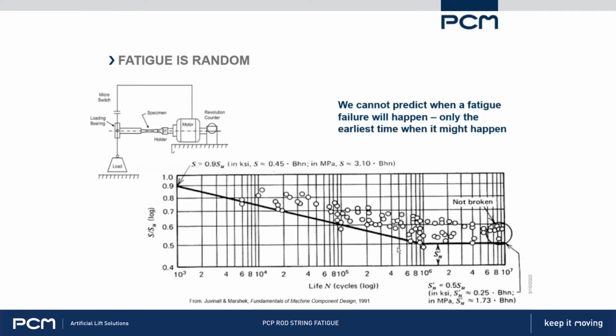And you can see there's a large amount of randomness here. So for example, at 0.6 or 60% of ultimate, the first failures are happening around 100,000 cycles, and we go over here and there's some specimens that lasted 10 million cycles without failing. So there's more than 2 orders of magnitude of difference between the first failure and some that haven't even failed yet.